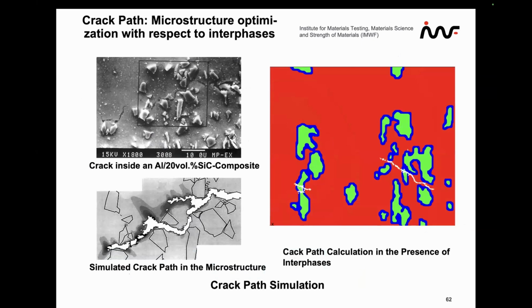Crack propagation, as I mentioned earlier, is in the focus of many of our analyses. The comparison with the experiment with this damage parameter shown earlier shows very good agreement in the microstructure. Here we polished away surface material, and we can use it to understand how additional phases, shown here in blue, influence this crack propagation behavior.